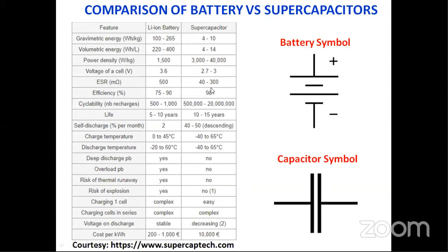Of course, on efficiency, in each and every cycle the supercapacitor has 99% efficiency, which means how much you charge, that much you are able to deliver. But in the battery, of course, it is 90, 75% and so on after the second cycle. In fact, the first cycle of any secondary battery will be a huge problem. That is, the Coulomb efficiency in the first cycle will be very, very low, nearly 60%. After that, you can get an efficiency of nearly 80 to 90%.